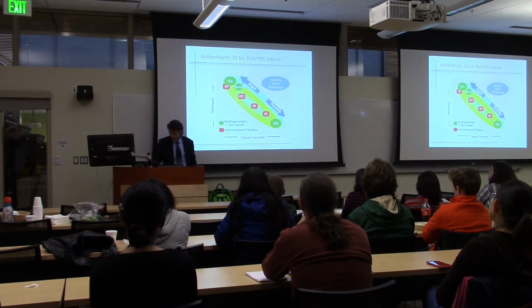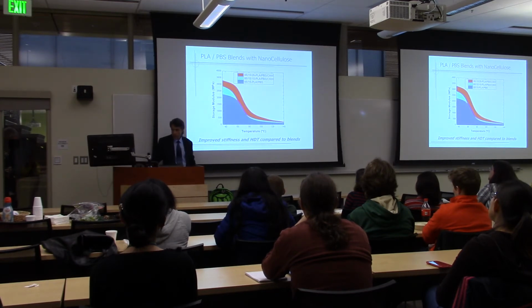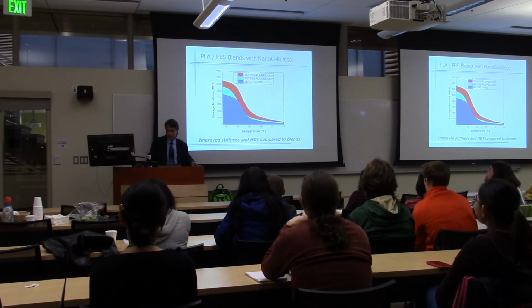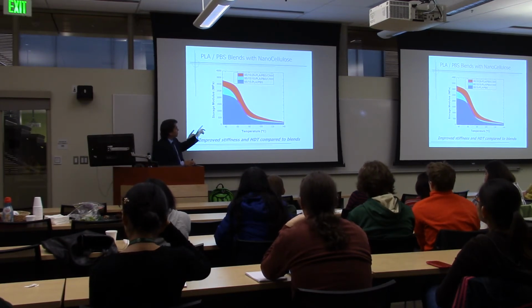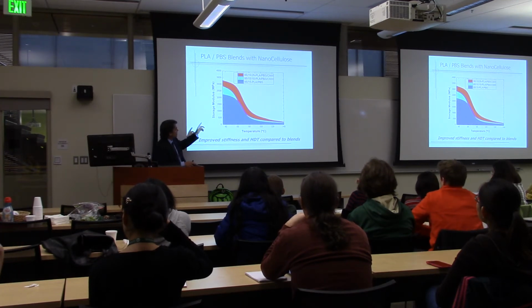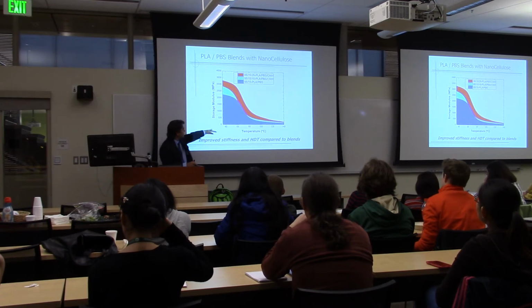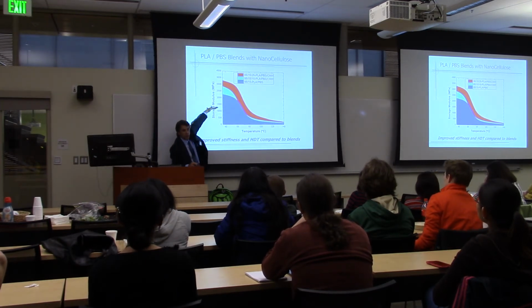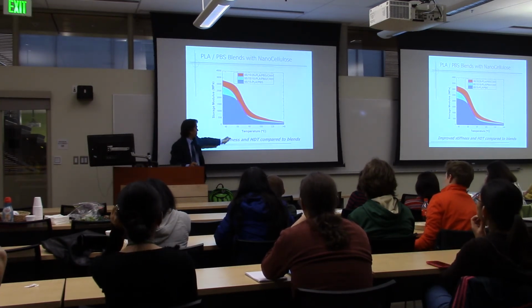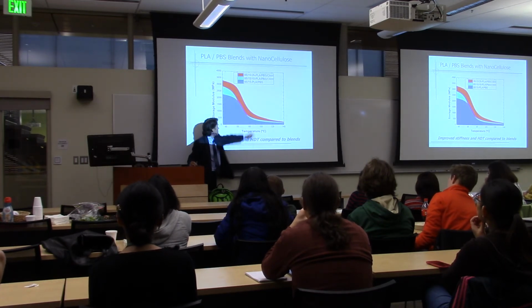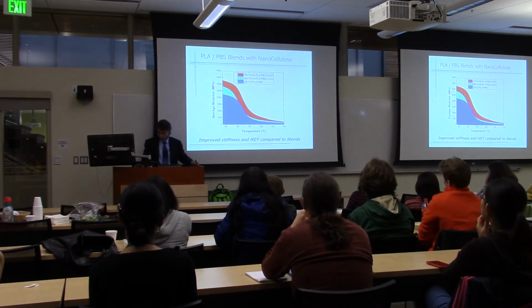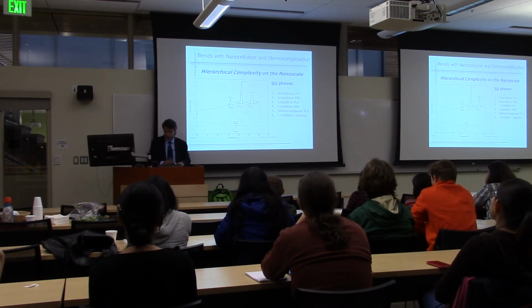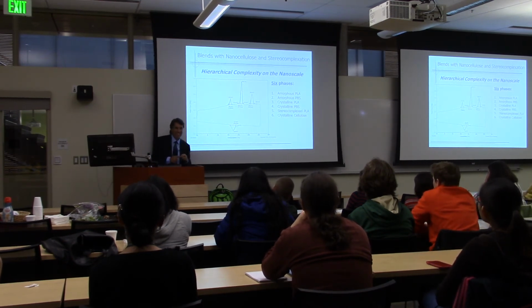And I know I'm running out of time here, but I will hopefully convince you that we've been able to successfully do that. This is a blend that's 85% PLA, 15% PBS, and then either 2.5 or 10% of the cellulosic nanowhiskers. And you can see we can, again, push that modulus up as a function of temperature. If you look at 80 degrees here, we're pushing up the modulus. And so it really starts to get complicated.